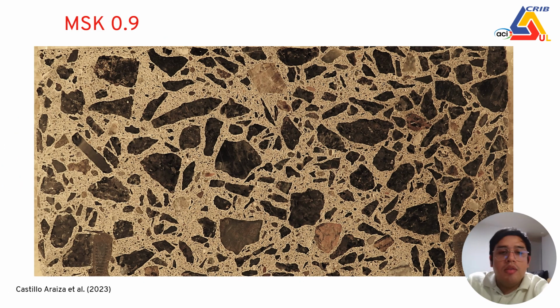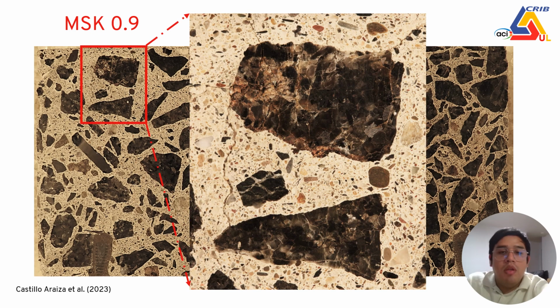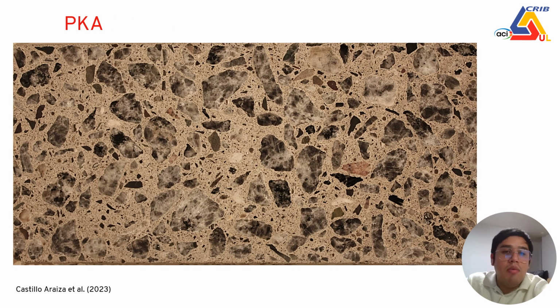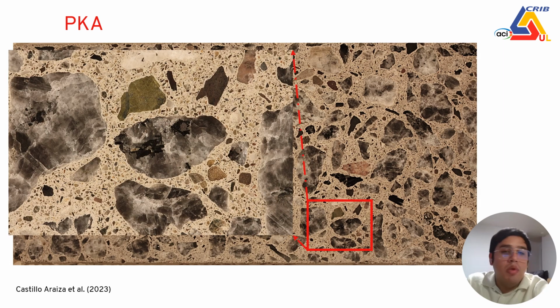So here you have an example of a concrete polished section after 35 days of electrochemical treatment. It's difficult to see on the screen, but if we zoom in, we can really observe the concrete affected by this reaction. And here you have an example of the non-reactive aggregate material that is not affected by this reaction. If we zoom in, we cannot observe any cracks, rust products, or cracking on the cement paste due to this oxidation reaction.